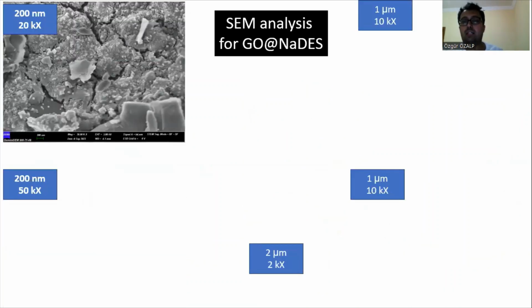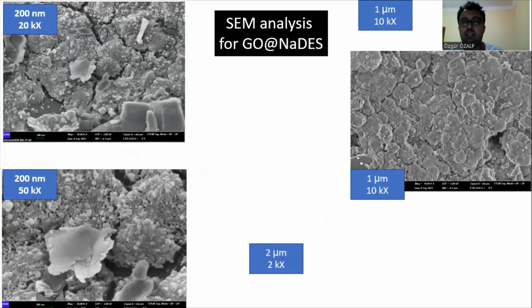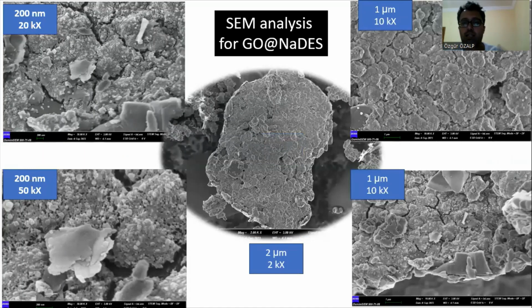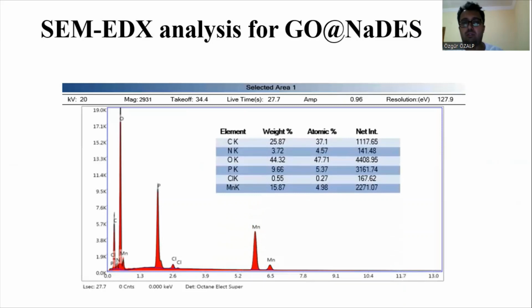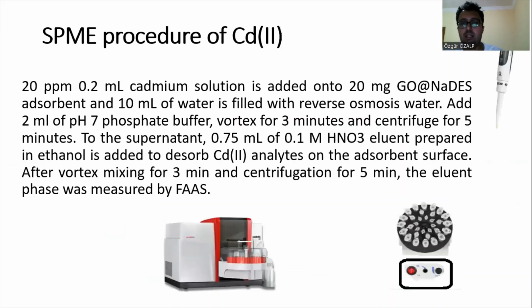Last of all, SEM and EDX. You can see different SEM images, and you can see small drops, which are the natural deep eutectic solvents, and the surface is graphene oxide. EDX shows different elements: carbon, nitrogen, oxygen, phosphorus, chlorine, and manganese from potassium permanganate.